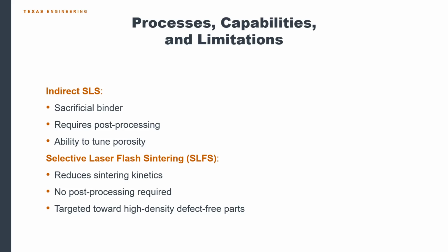The second method to overcome the difficulties with ceramics is by reducing the kinetics of sintering. And the way we do that is by a process called selective laser flash sintering, which is very similar to SLS, except that we add an electric field across the powder bed. This method doesn't require any binder or post-processing, and it is targeted towards high density defect-free parts.